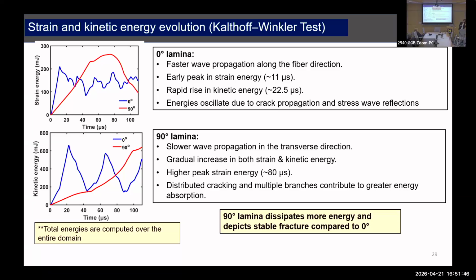If you compare with the quasi-static situations, I'm not sure if you paid enough attention, because I was rushing through so quickly. In the 90 degree lamina, the quasi-static response was not that impressive. 0 degree was much stronger because we were pulling along the fiber direction, but it looks like in dynamics, it might behave a little worse than the 90 degree case.